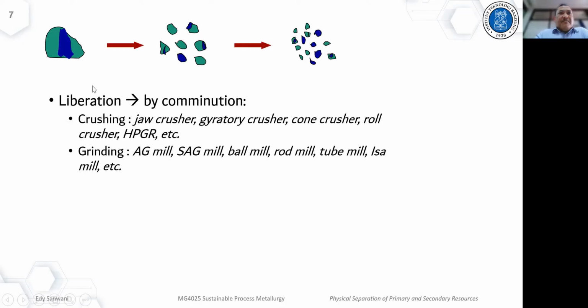Back again to liberation. Usually liberation is done by comminution, which comprises 2 main stages, crushing and then grinding. There are a number of equipment in crushing, for example, jaw crusher, gyratory crusher, cone crusher, roll crusher, HPGR, high pressure grinding roll, etc. And then after that, grinding. It can be autogenous mill, SAG mill, ball mill, rod mill, tube mill, ISA mill, etc. So in doing the liberation, usually in industry, we need to do crushing and then grinding.